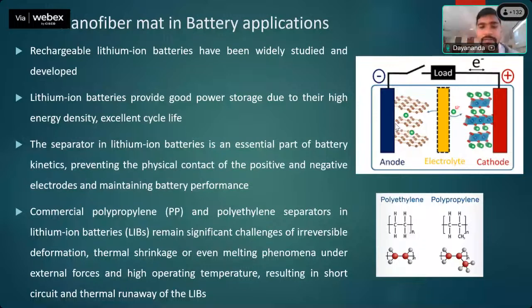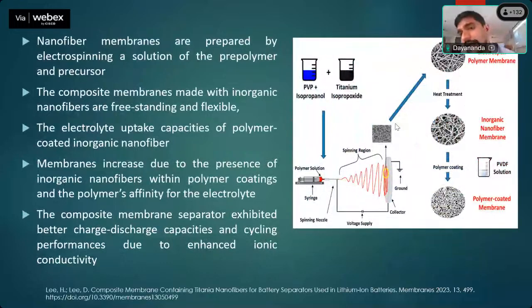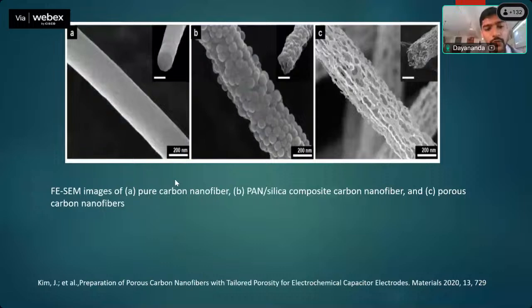The electrolyte can also be modified - PVP was dissolved in isopropanol, titanium isopropoxide was added, and that was used, showing improved efficiency. This image shows how the morphology of the nanofiber mat changes once doped with inorganic material. Here it is very smooth and clean, but once you dope with titanium dioxide or silica or any other inorganic substance, it changes completely - here we have a porous structure. It is always fascinating that once you add additives to the nanofiber polymer solution and alter the properties of the nanofiber, its efficiency and applications change completely.